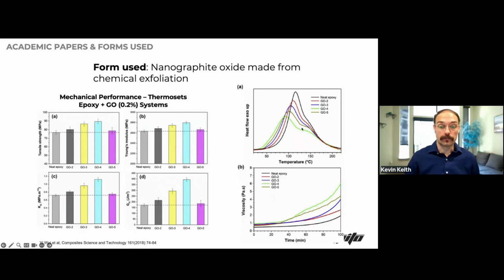So by the time you start getting higher and higher loadings, because you're choosing a graphene oxide to go into that system, you're getting a lower heat flow. So graphene oxide is an interesting material in the fact that, yes, it's graphene, it's within that GRM, but because of the properties and the characteristics that it shows, it's more insulating. So you're able to see that, hey, if I'm trying to hit some certain properties for mechanical performance, I can start looking towards what other GRMs are out there of how I can deploy that and really get the metrics that I'm looking for without overcomplicating things.